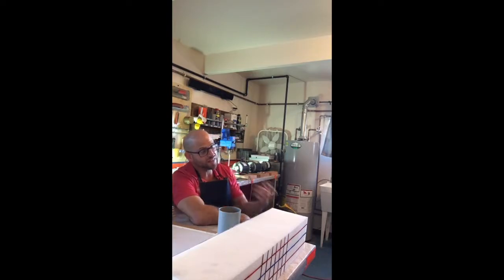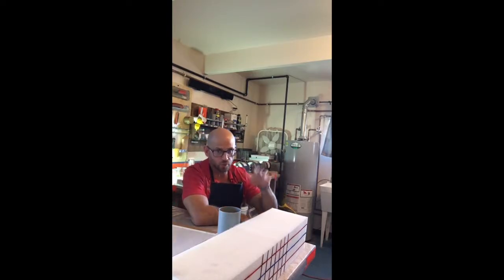So that would be the best way of doing it, which is not difficult to do. Anybody you're working with, you can tell them, hey, I want to make sure we order a low water cementitious concrete. I want to make sure that we're using an additive that has anti-efflorescence features and benefits to it. And then if that doesn't work, you can always, while the concrete is still in its plastic state, use a finishing aid to densify that surface so that, again, the salts and water can't migrate through to the top surface.